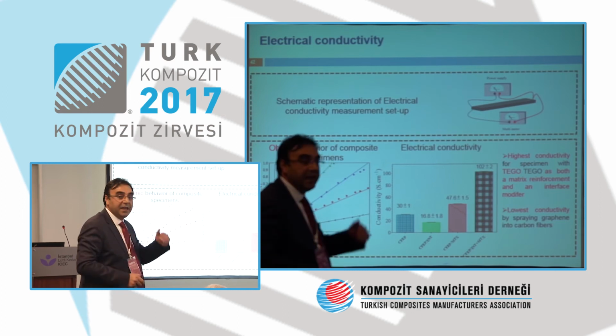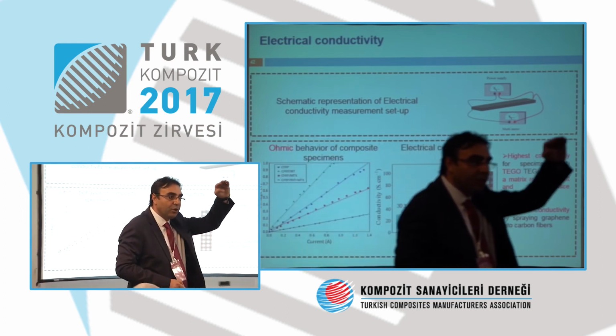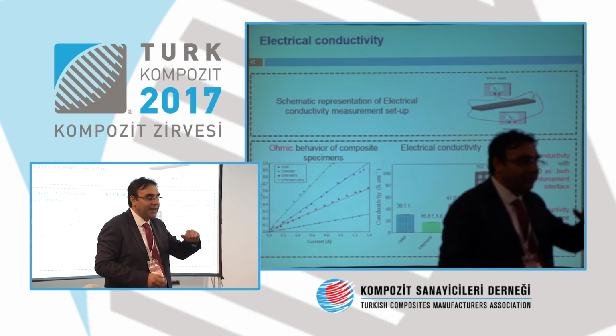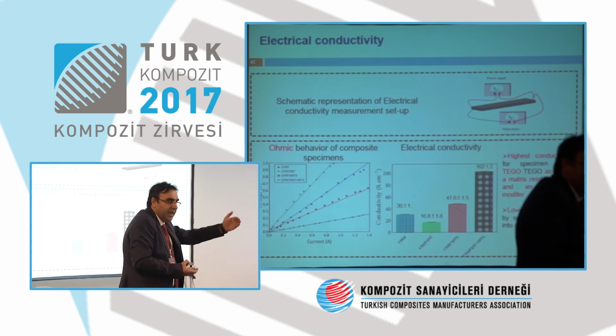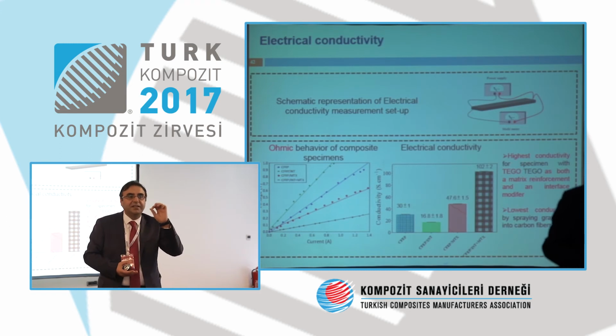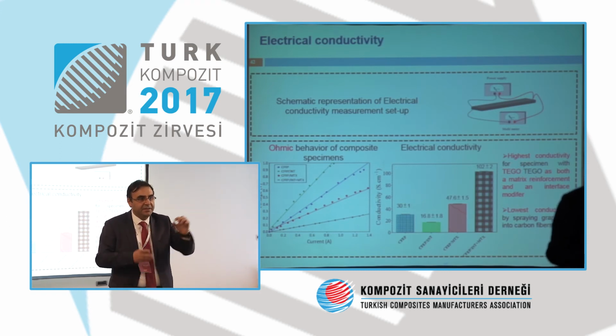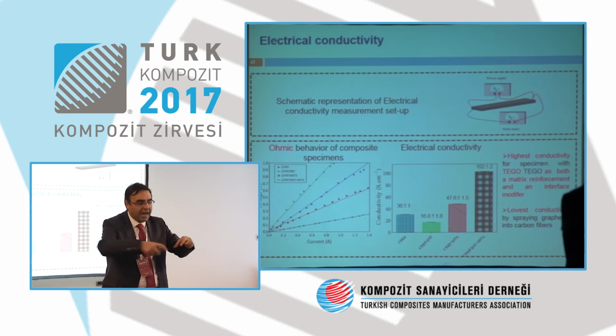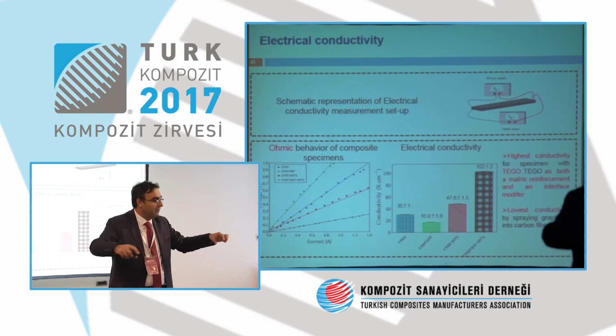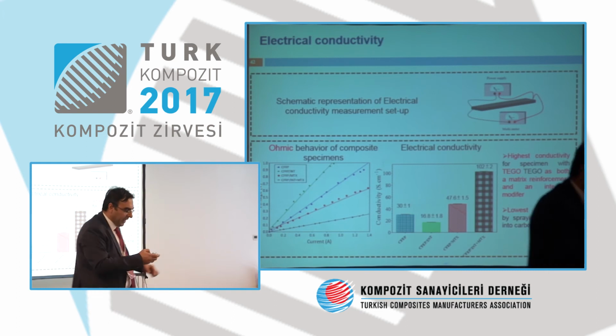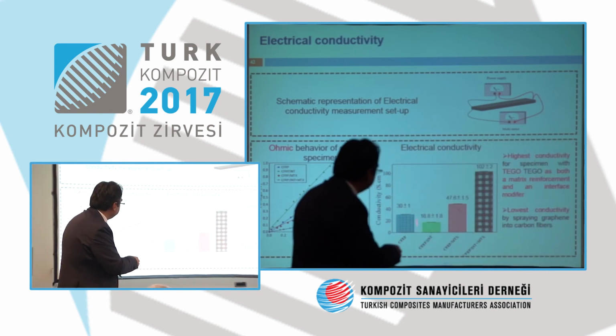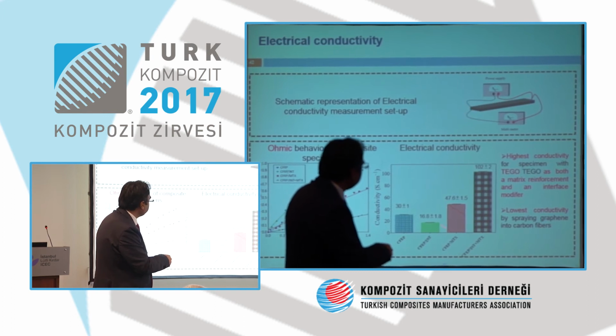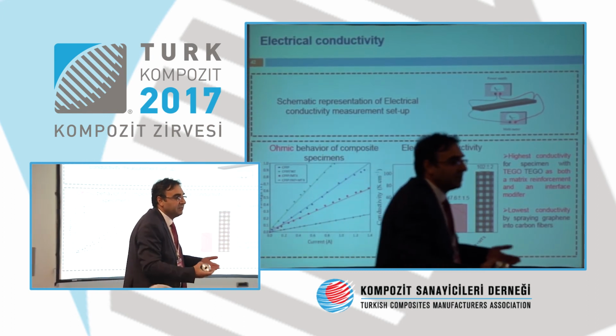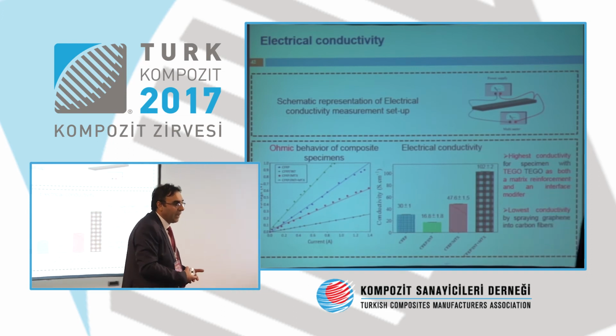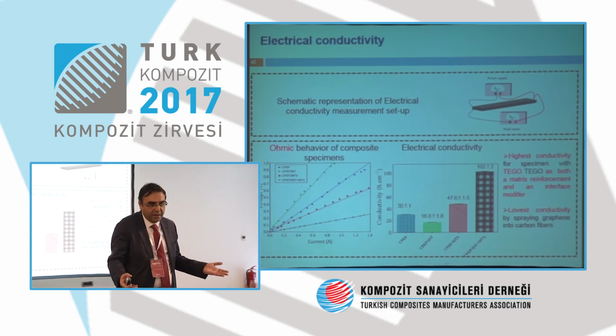And we observe that when we integrate this only to the interface, we have a notable drop in electrical conductivity. Naturally, you expect that value should increase. Actually, the graphene just acts as an electron trap. It doesn't allow electrons to propagate on the highway, the highway being your carbon fiber reinforcement. So that is the reason it decreases your electrical conductivity. When you add to the matrix, nothing surprising, because the matrix is a dielectric, non-conductive material. If you add something conductive, it will provide better electrical conductivity.